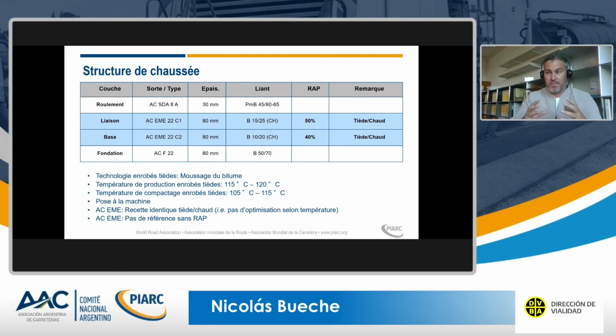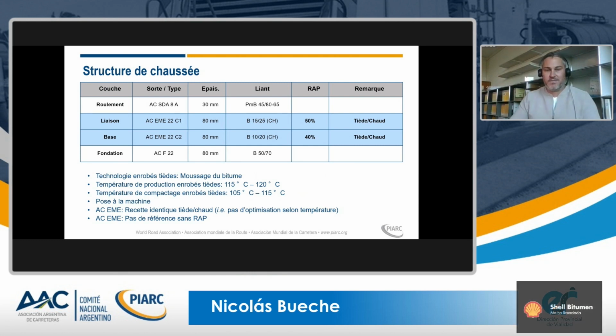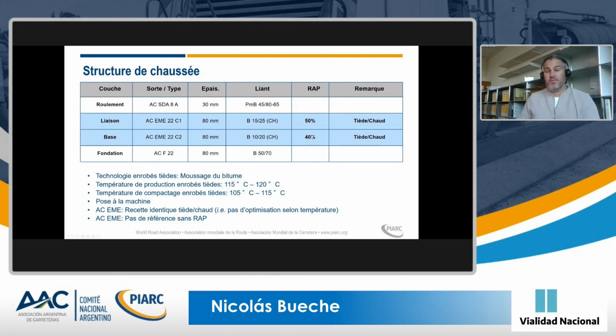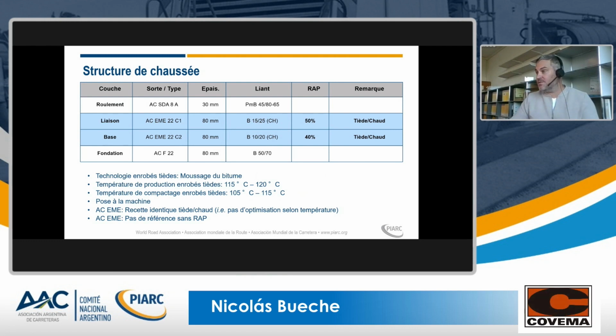If we look at the pavement structure, this is what you can see here in the table. So we have a top layer, which is, let's say, a classical low noise asphalt top layer, 30 millimeters. We call it semi-dense asphalt, but let's say it's low noise asphalt. And then we have 2 layers of high modulus asphalt, C1 and C2, 80 millimeters for each layer, with 50 and 40% RAP. Just a quick reminder, the current standard allows up to 30% reclaimed asphalt. With this project, we go to 40 and 50% reclaimed asphalt content.